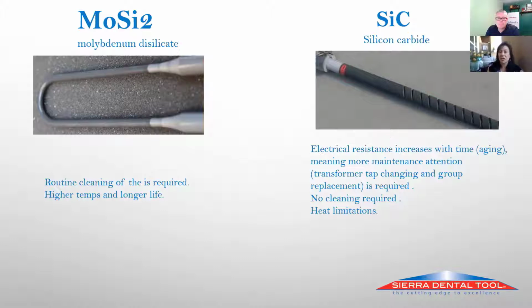Those traditionally, I come across a lot, like in the Nabertherm or the Dekema, and they're still great heating elements. These don't need to be purged, but they do not heat up to such a high temperature as the MoSi2. With the silicon carbide, you can go up to 1560, but if you pass 1530, you are shortening the life of those elements. And when you change them out, you do have to change all of them at the same time.